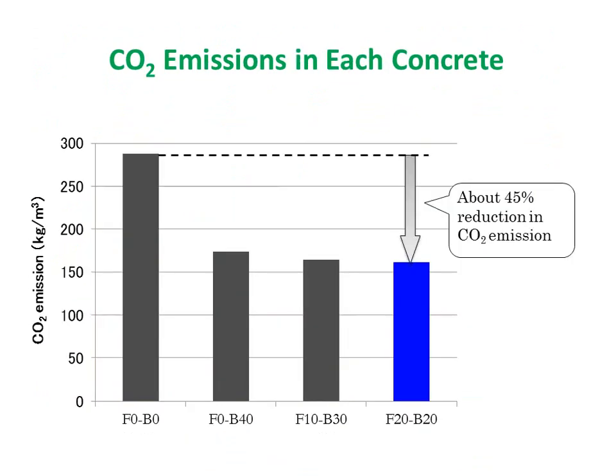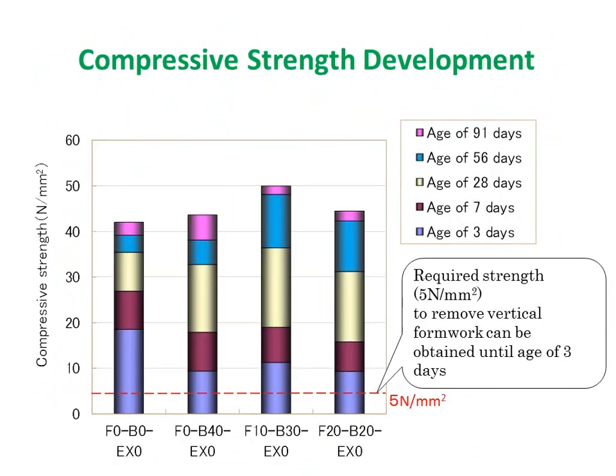This is one point. Not much compared with the 80%, but considering the other performance, like compressive strength development. This is the ordinary Portland cement, and 40% blast furnace slag, and 10% fly ash, 30% blast furnace slag, and this is the 20% fly ash and 20% blast furnace slag. So we can see that there is a requirement at the early stage to remove vertical formwork. In Japan, that number is 5 Newton per square millimeter. So if you utilize this concrete, that requirement is satisfied. And then finally, the 91 days strength development is greater than the ordinary Portland cement, as you can see.